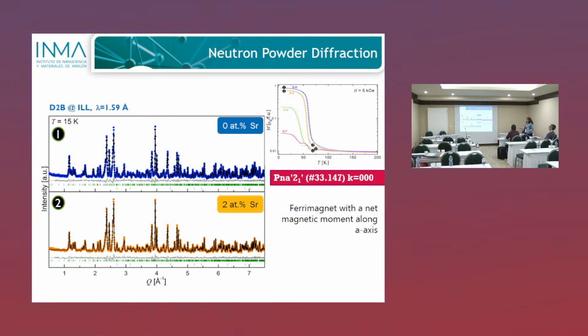This is a measurement for the pure sample with no strontium, and this is a measurement for the 2% strontium sample. And the refinement is done using the Rietveld method with the FullProf program, and taking into account, of course, the magnetic contribution to the diffraction pattern. For this, we use the formalism of magnetic space groups. And the space group in this case is indicated here. And you see that we have a propagation vector for the magnetic structure, which is 0, 0, 0, which means that the magnetic cell is the same as the crystal cell.